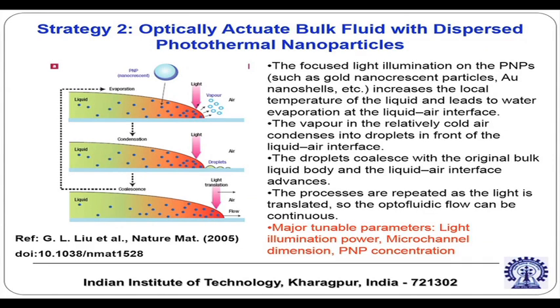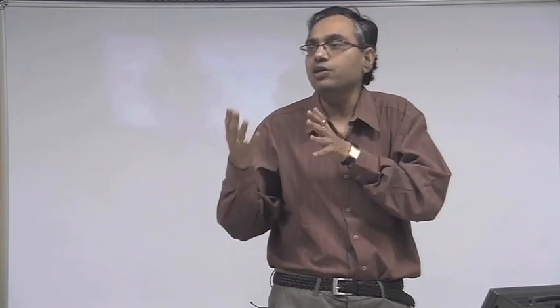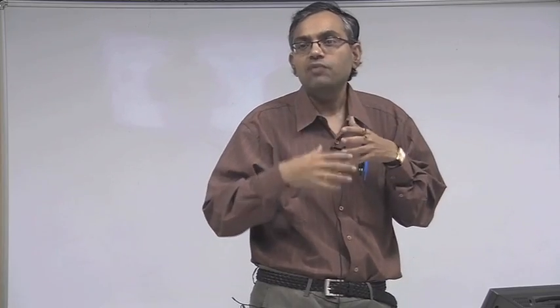So what are the major tunable parameters? The light illumination power, the laser power, the microchannel dimension, and the photosensitive nanoparticle concentration are the parameters which can be tuned to alter this phenomenon. So it is possible that by using light one can create a change in surface energy, and a change in the bulk also, that will eventually translate into a change in contact angle. These two technologies, either individually or combined, can give rise to an optical modulation of the interfacial phenomenon. So it is possible to modulate the surface tension optically.